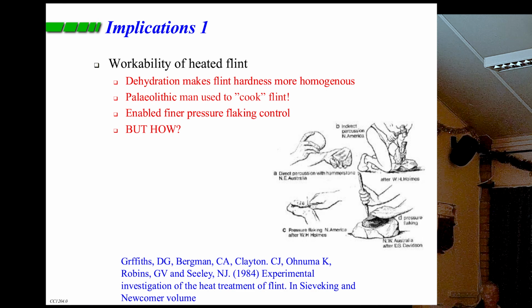The problem was that where we have a lot of lepispheres together, they're comparatively hard. If you fracture flint and your fracture hits a little clump of lepispheres, the fracture shoots off in an unpredictable direction. Whereas if you cook the flint, it actually makes the internal structure of the flint a lot more homogeneous.